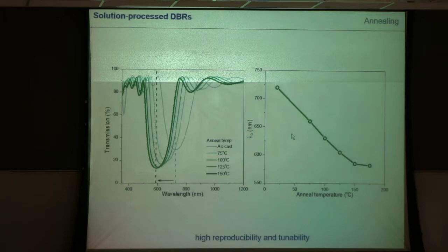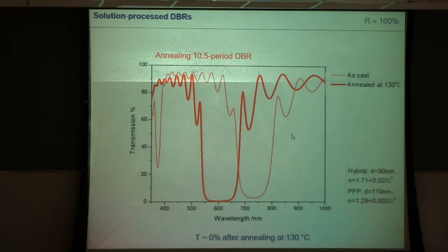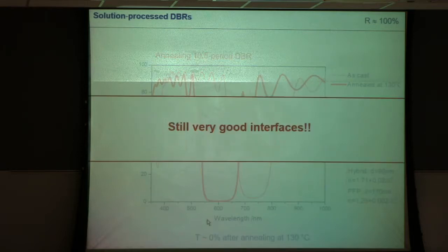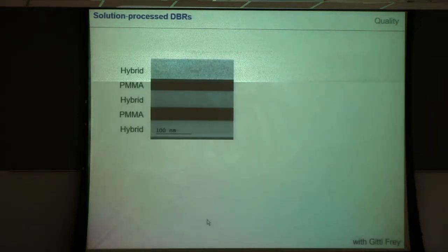We were a bit surprised because we sometimes have 40 layers in there, which we anneal, but obviously the layers are actually not that thick. So like that, we can, for instance, optimize a mirror that doesn't have a full reflection. When we anneal, we can get to 100% reflection. Clearly, we must know that the mirror does shift after the annealing. And the key is the materials work so well because we have very, very good interfaces. And I think here they're actually equivalent to what you get with inorganic materials.